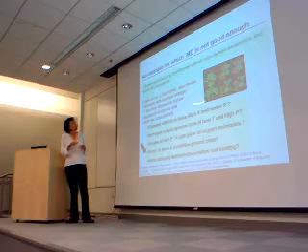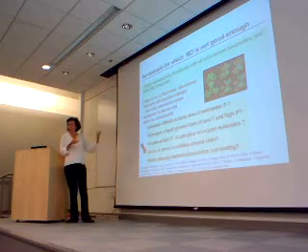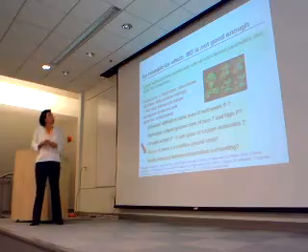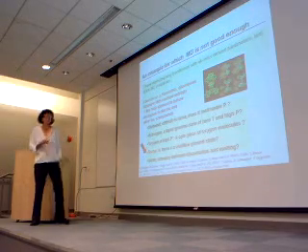because simulation times will be too long and because you will never sample all the configurations that are relevant to solve the problem. So here you have to do something different, and one way to do this is to couple your first principle calculation, not with molecular dynamics, but with Monte Carlo. In particular, here we have used the first principle electronic structure calculation to come up with an Ising Hamiltonian that we have used to do Monte Carlo simulation.